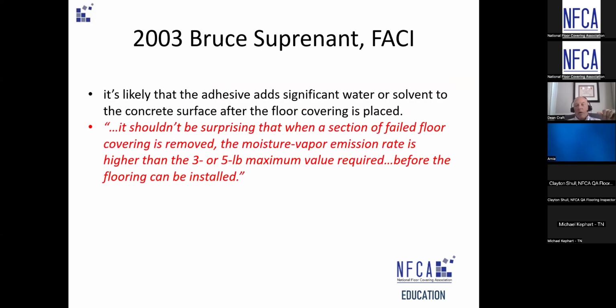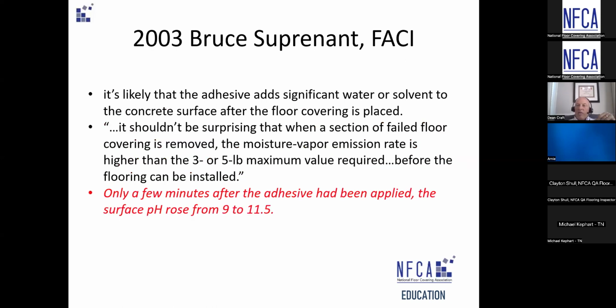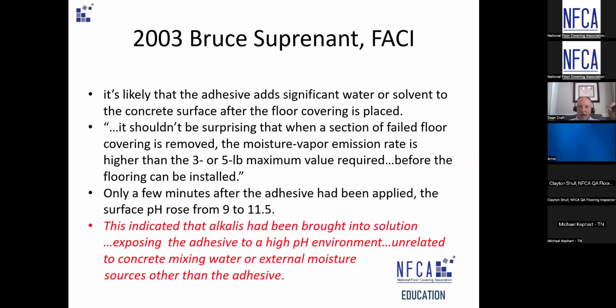So keep that in mind. And what they found is almost invariably after they installed and removed the flooring, that it was almost a fait accompli that it would be in excess of the 3 to 5 pounds of moisture. They also tested the adhesive. They noticed that within just a few minutes after spreading the adhesive, the surface pH went from 9 to 11.5. And the only source of liquid that allowed those residual hydroxides or carbonates to go into solution came from the adhesive itself. There was no other source of moisture. This was not days and weeks and whatever. This was nearly instantaneous.